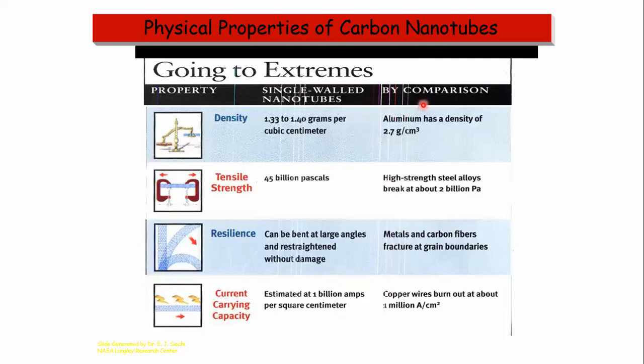Now carbon nanotubes have been compared with some other materials. Like density: aluminum has a density of 2.7 grams per cc, and carbon nanotubes have 1.30 to 1.4, so almost half the density. Tensile strength is around 45 billion pascals, whereas high strength steel alloys break at around 2 billion pascals. Then it has better resilience, and current carrying capacity is very high. It is estimated to carry 1 billion amperes per square centimeter, but copper wires burn out at about 1 million amperes per square centimeter. So this can be done.